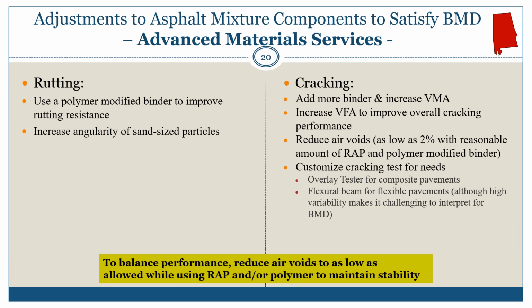From a cracking performance, Brian recommended trying to add a little bit more binder and increase that VMA. Increase your voids filled to improve the overall cracking performance. That was a key factor that Brian said that he sees in a lot of his designs. He also suggested that state agencies are going to have to try to reduce air voids a little bit, maybe as low as 2%, to allow for a reasonable amount of asphalt binder in that mix.